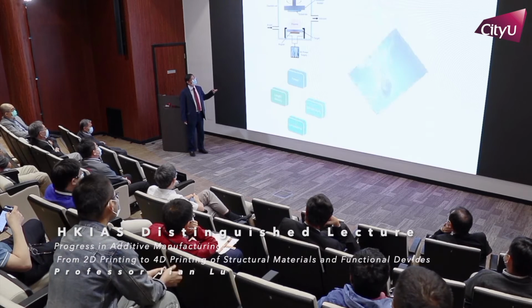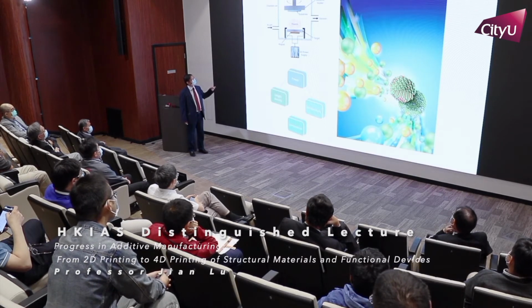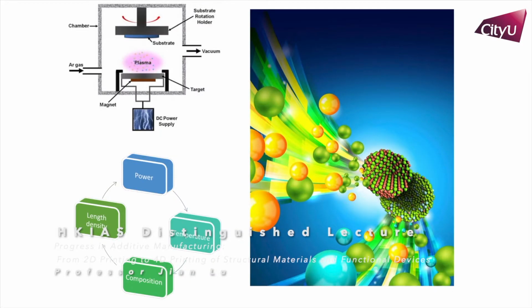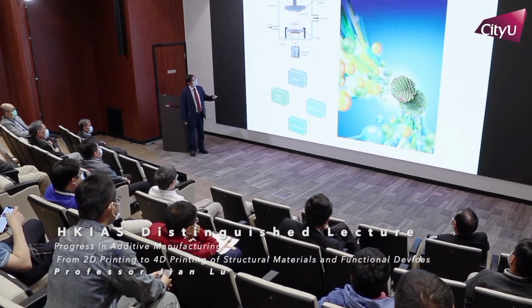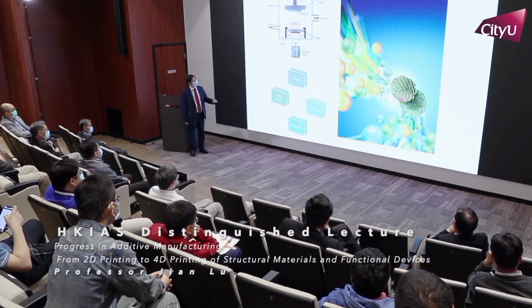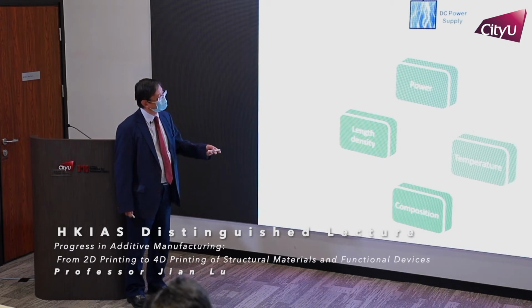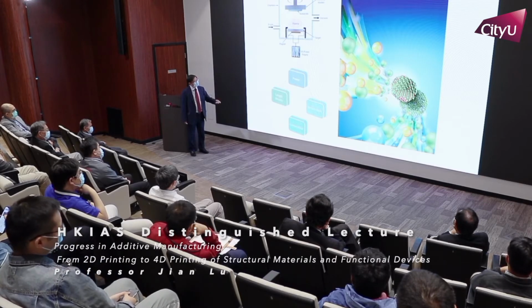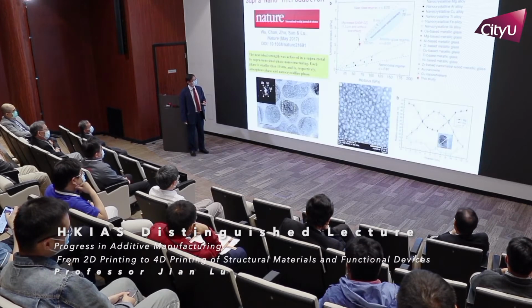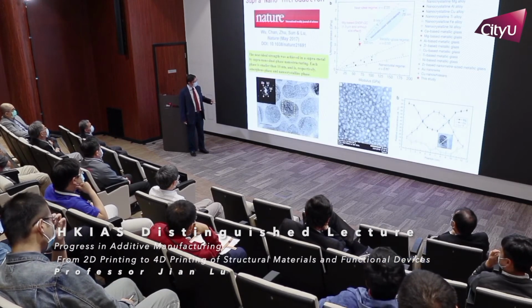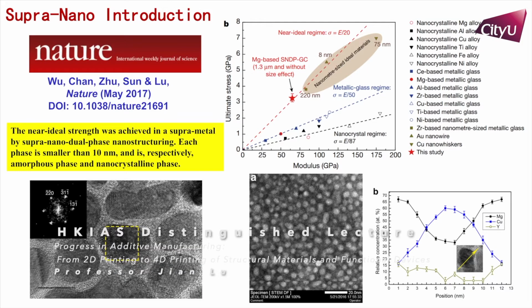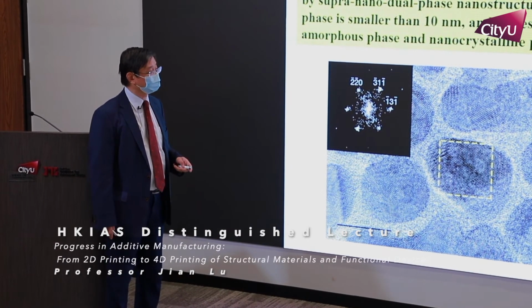And this is one kind of additive manufacturing, because we have a substrate, and this is PVD, quite classic PVD. The main importance is how to design the substrate. During the PVD process, what we have successfully obtained is the phase separation. After phase separation, we have a material with a crystal, and the remaining part is metallic glass. As you may see here, this structure is very nice. We have crystal distributed regularly, and metallic glass, amorphous material, also distributed regularly.